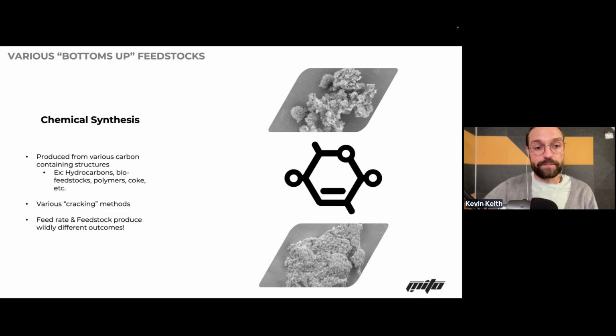So, with those feed rates and feedstocks, you can produce a wide range of different morphologies, as well as chemical structures. Being that you're feeding hydrocarbons into the system, depending on what hydrocarbon you feed in, if you feed it fast enough and at a cool enough temperature, you can have PAH particles on there, which has pros and cons depending on what application you're going for. So you can create highly wrinkled structures, highly flat structures, very small, large.